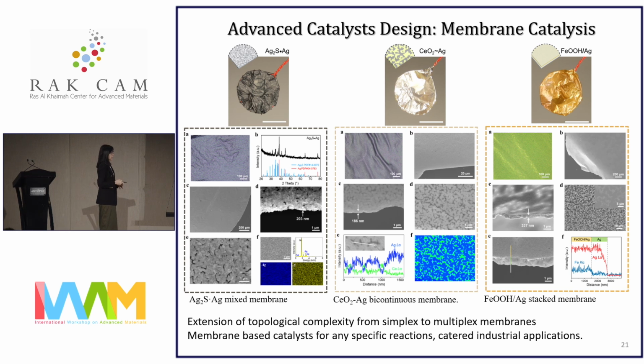So other than a simplex membrane, we also tried to prepare a multiplex membrane, which is derived from a mono-composition of a silver membrane. This includes silver sulfide silver, cerium oxide silver, as well as iron oxide hydroxide silver. This one is essentially one membrane grown on top of the other membrane, seamlessly integrated with bifacial features that combine the best of both materials together in a singular structure. So here are all the materials characterization to prove the materials composition as well as structural design of the complex